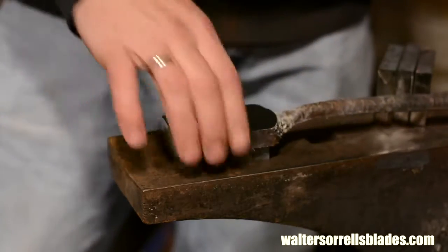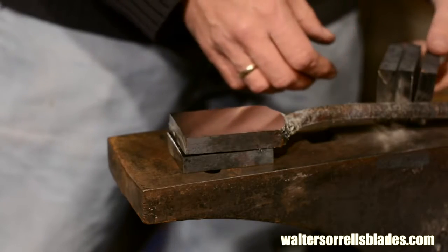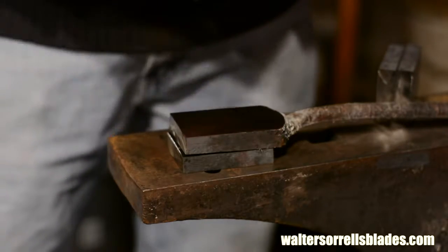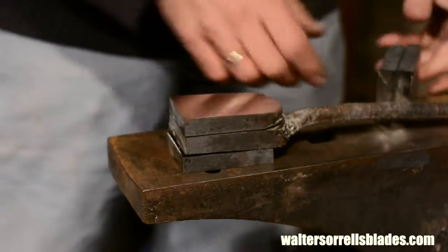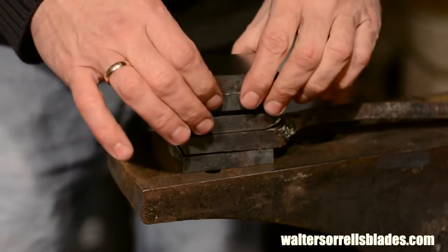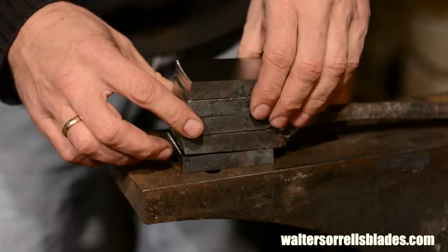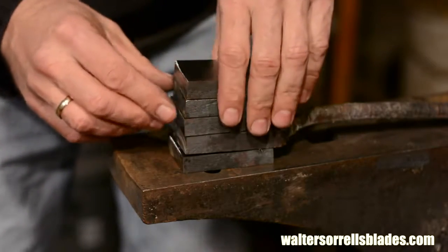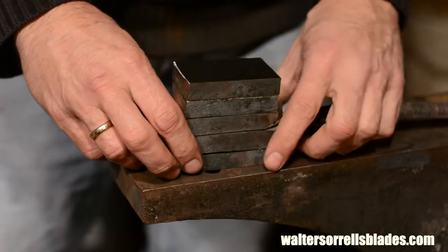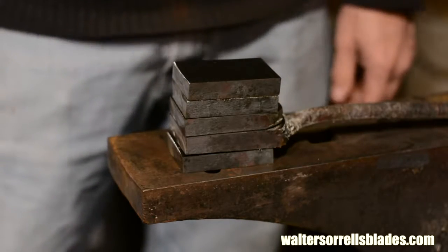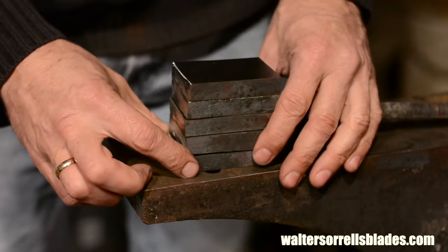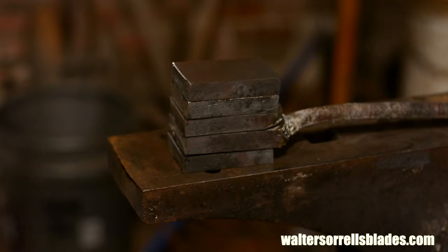Whether you cut them off or not, though, you're wise to be aware of where the ends of the original billet were and to bury those ends inside the billet, both facing in the same direction. That way, any problem welds are least likely to show up in the final blade. You can cut these tabs of crappy steel off if you want, but I actually like to use them as a sacrificial piece on the end where I can attach my handle. That way, at the end, I'll cut off a goodly chunk of the final billet, eliminating problem welds and any MIG weld inclusions that might have ended up in the steel, leaving all the good stuff for my blade.